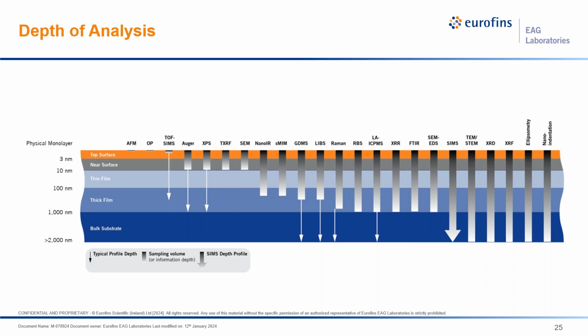But with the sampling depth of 1 to 10 nanometers, we can also look at intentional ultra-thin films such as self-assembled monolayers, passivation, plasma-treated surfaces, unintentional thin films, say diffusion to the surface, or other contaminants.